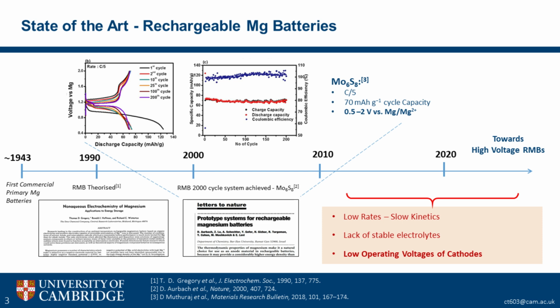So since then, in the 1990s, Gregory et al. proposed a rechargeable magnesium battery in a non-aqueous system. And 10 years later, Doron Aurbach's group published the seminal paper that most people here will know, where he demonstrated the first rechargeable magnesium battery prototype that was stable up to 2,000 cycles. And I'm going to focus in on the cathode of this paper, which was the Chevrel phase molybdenum sulfide. And to date, almost 24 years after this discovery, it's still the benchmark cathode material used in the field.